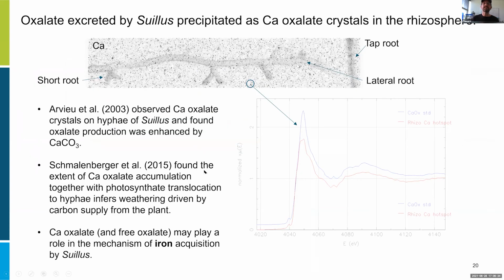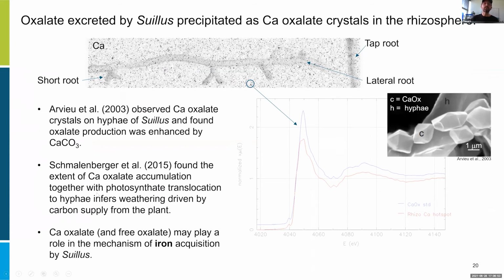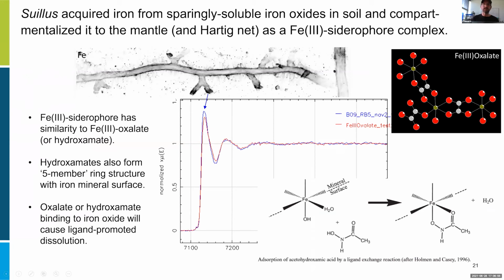And so what we're finding is that the fungus has pumped a bunch of oxalate into the rhizosphere, which other researchers have observed in the past. And this oxalate is at various stages bound with calcium, and in other stages it's free. And we believe that this mechanism is related to iron acquisition, because when we explore the iron speciation in this rhizosphere, everywhere we look in the fungal mantle, we find the same iron 3 complex.